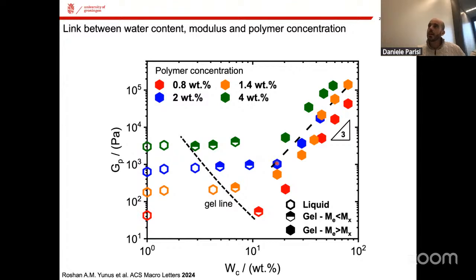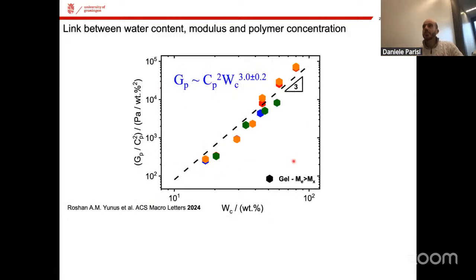And then eventually, for very high content of water, there are many more crosslinks than entanglements, so that the network is dictated by the number of crosslinks rather than the number of entanglements. And you see that there is a huge power law relation between the modulus and water concentration. So we applied some polymer physics here. Usually we know that if we divide the modulus by the polymer concentration to the power of 2, this function should scale and put all the data together into a master curve with the crosslink density. Here, instead of the crosslink density, we have water concentration, but effectively it's an effective crosslink density. So you see that when we apply this, all the data collapse together.